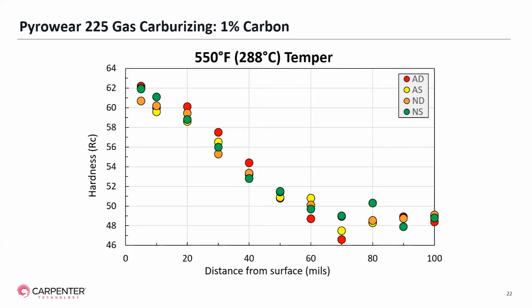I'm showing 550 in this particular instance in the interest of time. But you can see that regardless of the variant, whether it was given an intermediate austenization or not, whether it was single tempered or double tempered in this instance at 550 degrees Fahrenheit, we're still able to get surface case hardnesses that range from about 60.5 up to 62 Rockwell C, and an effective case depth, that is the depth at which the hardness falls below 50 Rockwell C, of approximately 60 thousandths of an inch or 1.5 millimeters.